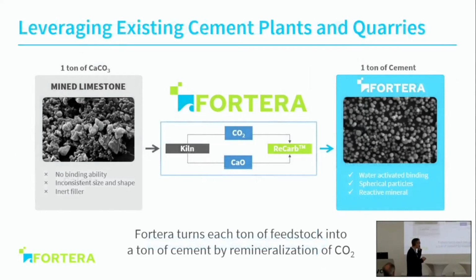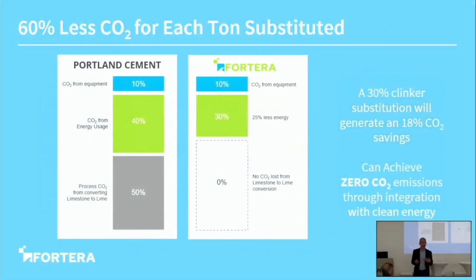So what Fortera has done is to develop a process to transform mined limestone into reactive calcium carbonate. How do we do that? We first dissociate the lime from the CO2. The lime is dissolved in the process, and then the CO2 is remineralized to form the reactive calcium carbonate. What is the benefit? First, it requires less energy than to produce Portland cement. And second, and I should have said first, the process emissions are remineralized, which means that for each ton of reactive calcium carbonate, we will emit 60% less CO2 than Portland cement.